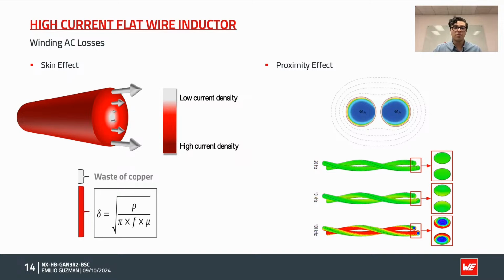frequencies. For the proximity effect, it refers to the tendency of the current distribution in one conductor to be affected by the magnetic fields generated by nearby conductors. This causes the current in one conductor to push on the current of another conductor, also increasing resistance and impacting the efficiency. Here, the flat wire also helps on this issue by providing a larger surface area, allowing the current to spread more evenly. Also, the packing density minimizes the impact of magnetic fields in other conductors close by.